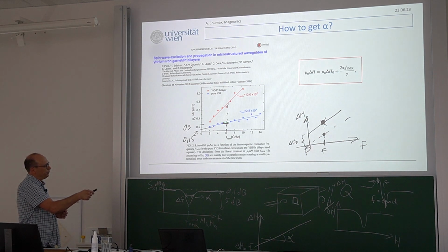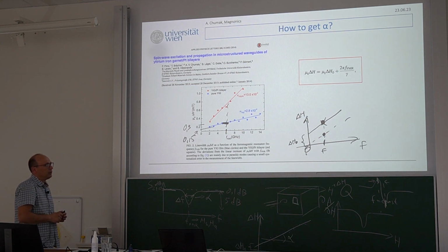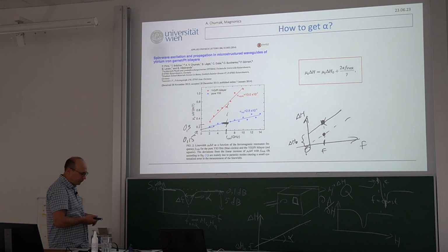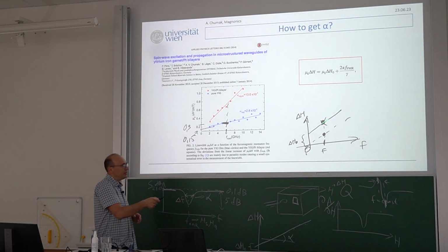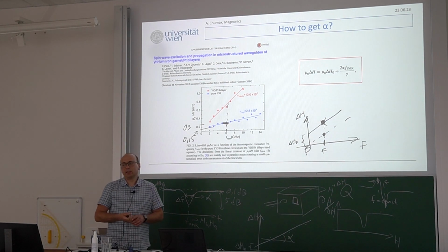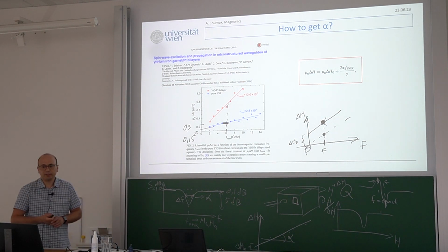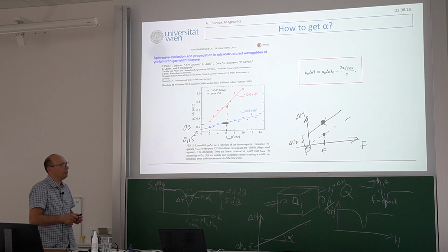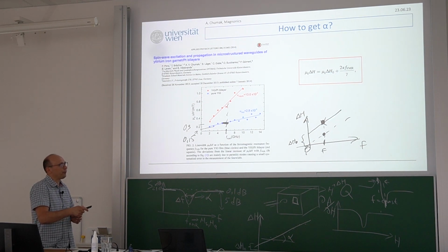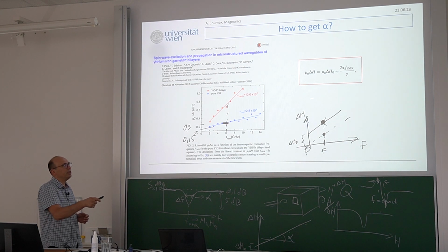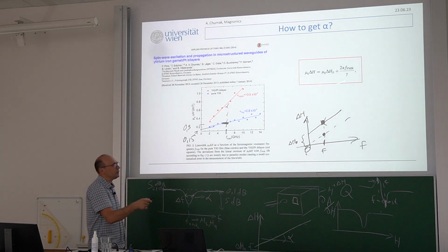And pay attention also that sometimes people report a very small alpha. Alpha is this angle, and when you look at this, it looks very impressive that alpha is very small, but in some cases what happens is that this delta H0 is simply so large that the line stays here, and it's already very flat because damping is given mainly by delta H0, by some other physical processes.